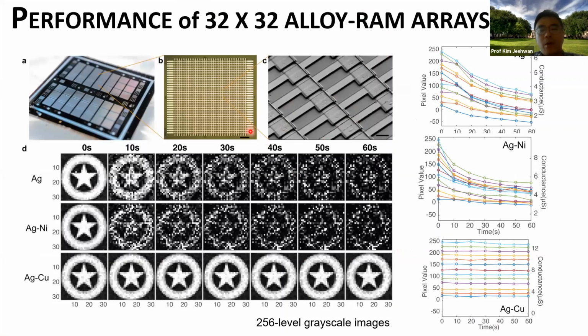With this array, we are able to do some inference tasks. First, we tried to update grayscale images on the memristor arrays. 256 level grayscale images were updated onto this device. Again, as you can see here, the updated image is decaying for the pure silver and nickel silver devices, but the silver copper device retains the updated image for a long time, which is simply because we have excellent alloying behavior in this silver copper based alloy RAM.